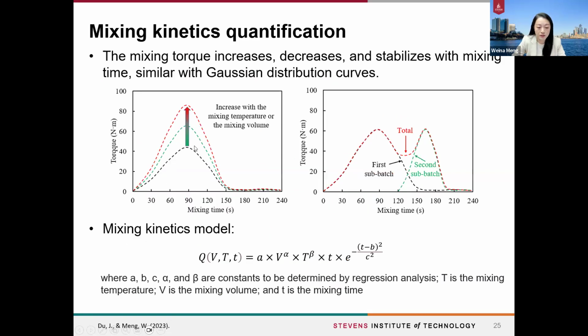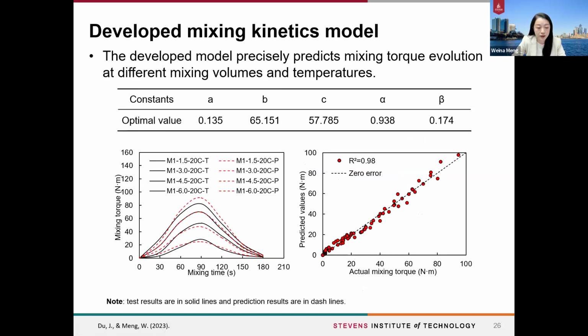And look at the mixing evolution curves. We saw that it's quite similar to Gaussian distribution curves. So based on that, we proposed a mixing kinetics model to describe these curves. As shown here, A, B, C, alpha, beta are constants, which can be determined by regression analysis. And T here represents the mixing temperature, V is the mixing volume, and t here is the mixing time. So again, by the regression, we can determine the constants for the model and use the model to predict the mixing kinetics curves. We developed this model because we want to use it to optimize the mixing process for any large volume of UHPC.